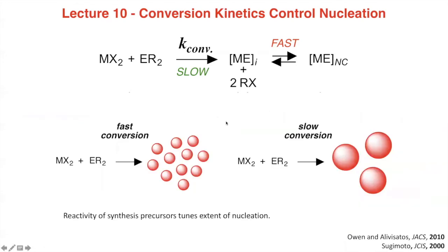All right. So along comes another fellow named Tadao Sugimoto, and Sugimoto realized that these types of kinetics can actually depend upon how fast the monomer formation kinetics happen. Sugimoto taught us that reactions that are really rapid, that produce solute quickly, will have a tendency to make many more small particles. And if these kinetics are slow, then you make fewer particles that end up larger in size. And so this is an intuitive concept, I think, if you're familiar with this nucleation barrier stuff.